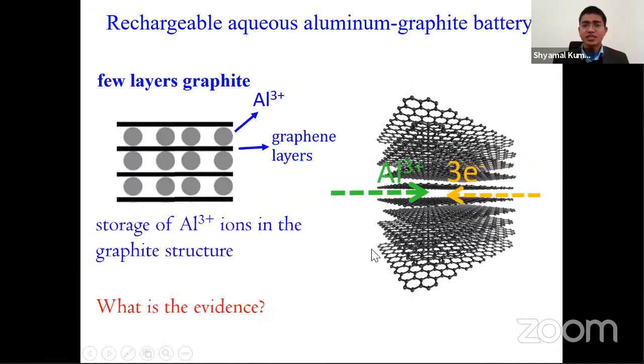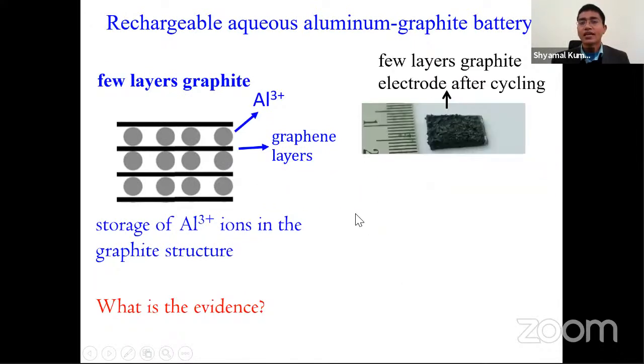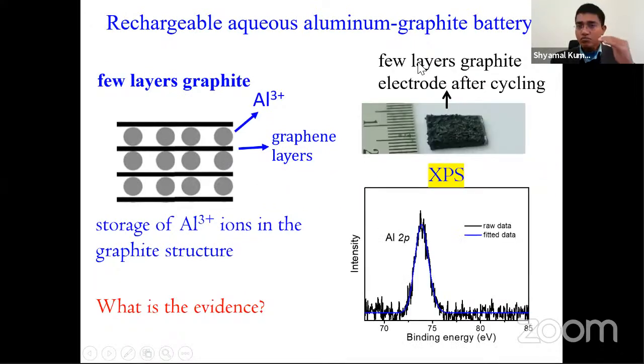Now, one obvious question is: what is the evidence that aluminum ions are going inside these graphene layers? It is sitting inside the graphene layers. For that, we took the electrode after running the battery for several cycles, and we performed XPS. We used XPS techniques to find out whether aluminum is there or not, and we see the signal of aluminum.